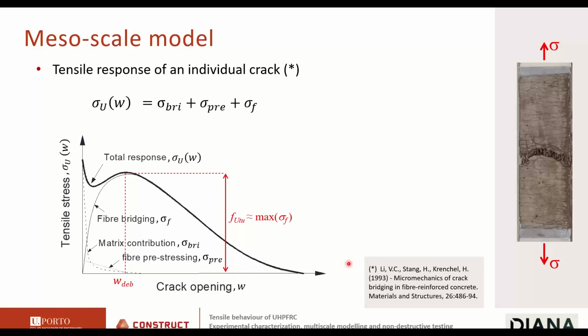So we need to describe the response of each of these cracks, and there are many of them on the specimen. This is the behavior of a single crack. It starts at the crack opening of 0 and continues until complete fiber pull-out. The total response at each crack is the sum of 3 contributions. This is based on the works of V.C. Li, referenced in this paper. The biggest, most important contribution is due to the fibers, the fiber bridging stresses, sigma.